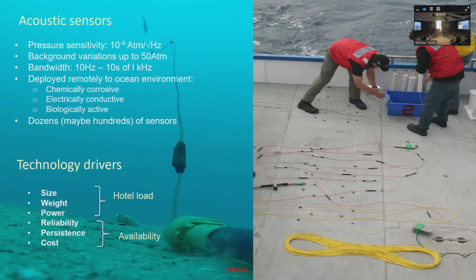So why do we need extraordinary materials in order to do sonar? What I've just done here is summarise some of the challenges of underwater acoustics. So the first thing, you require devices with a pressure sensitivity to be able to measure pressures of the order of 10 to the minus 9 atmospheres, in an environment where the background variations with depth can be up to 50 atmospheres as you go from sea level down to hundreds of metres in depth. So if you think of that in terms of a precision, you're talking about 1 part in 10 to the 10, so better than 1 part in a billion.